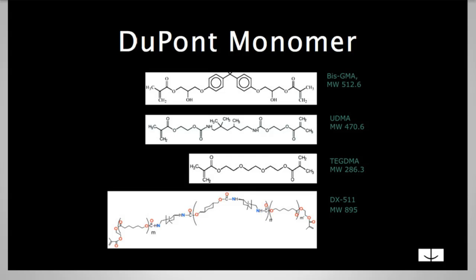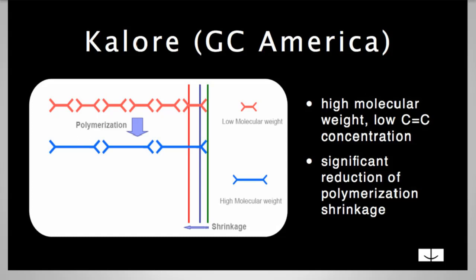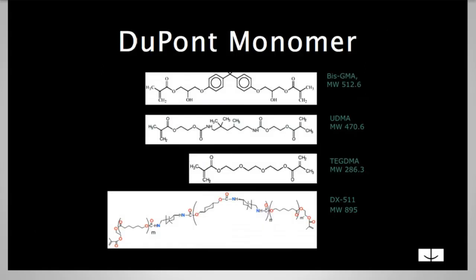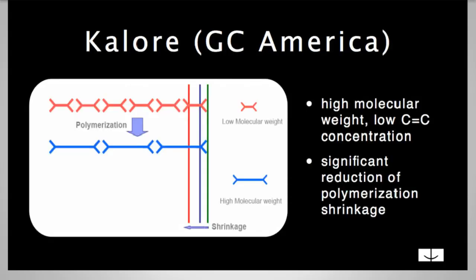So essentially what happens is that when you have a larger, heavier molecular weight monomer, which is much, much longer, right? If you look at the monomer here, look how long this is versus this chain. So when you have a heavier monomer, you actually have fewer areas where they can polymerize, hence you have less overall shrinkage. So Kalore is 82% filled by weight, a very, very heavy composite, and hence their shrinkage stress is very low.